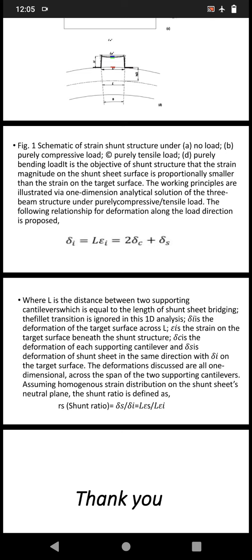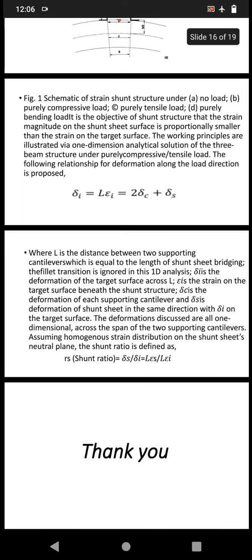Delta I is the deformation of the target surface across L, and epsilon is the strain on the target surface beneath the shunt structure. Delta Ci is the deformation of each supporting cantilever, and delta S is the deformation of the shunt sheet in the same direction as delta I on the target surface. The deformations discussed are all one-dimensional across the span of the two supporting cantilevers. Assuming homogeneous strain distribution on the shunt sheet's neutral plane, the shunt ratio is defined as RS, equal to delta S divided by delta I.